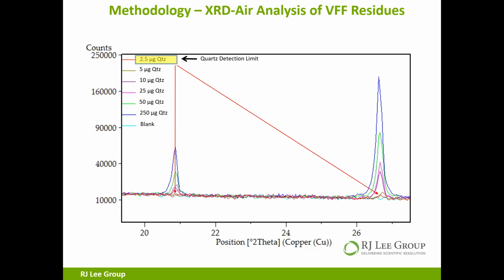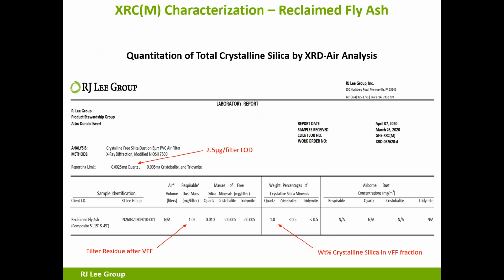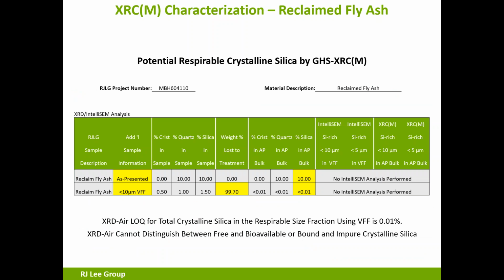Now we're going to run it through our XRD air analysis method, which has a detection limit of 2.5 micrograms per filter. Okay, and you can see the little tiny peaks down there on the bottom. Barely detectable, but functional. Remember, we had 1.06 milligrams. It varies a little bit because we actually have a couple of filters at play here. The weight percentage in total of the VFF fraction was 1.0 weight percent crystalline silica. So we run that back into the 99.70, we are now less than 0.01%, and we have not only passed GHS, we have passed Prop 65, and this product is cleared.